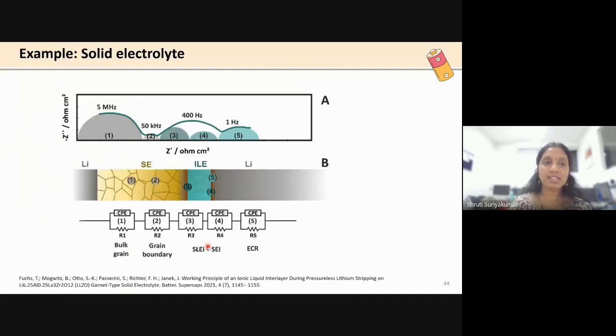Moving on, this is another example of a solid electrolyte. We have solid electrolyte systems. The system is quite complex. So in this work, they have a solid electrolyte, and they also have added some ionic liquid on the interface, and then they have assembled a symmetric cell. So you have a lithium, a solid electrolyte, and an ionic liquid electrolyte, and then a lithium. So you can again deconvolute it into 1, 2, 3, 4, and 5 different phenomena.